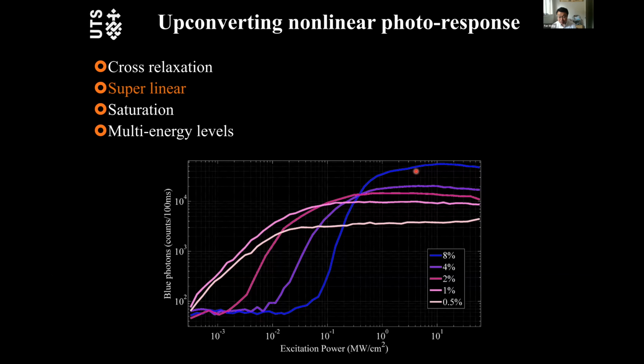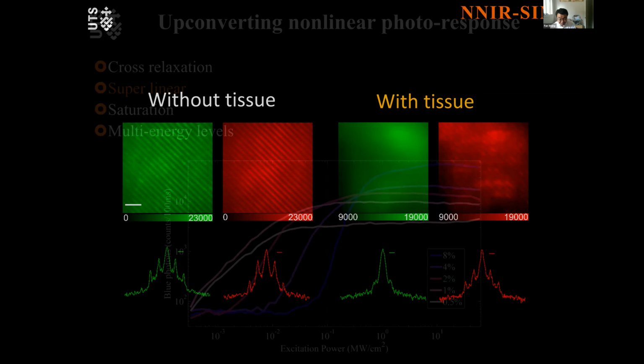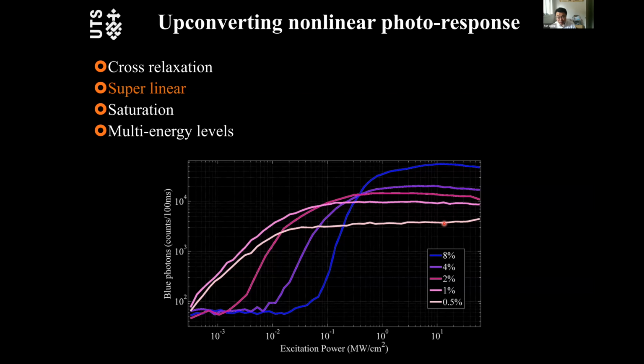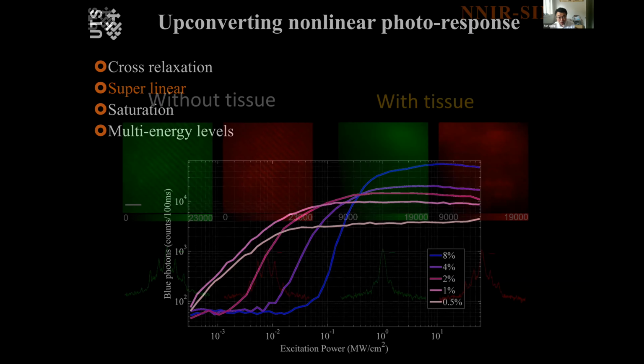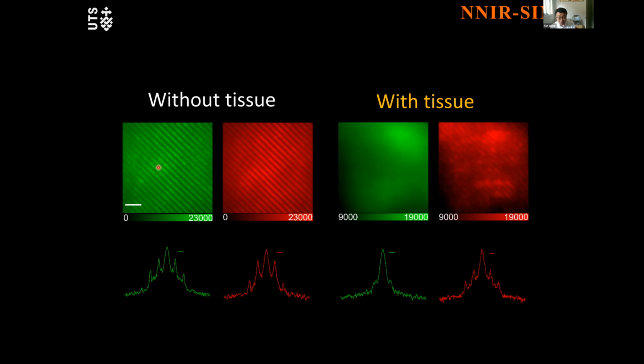And this power-dependent curve means that if you shine some pattern onto a nanomaterial, the response can be different. It would carry more resolution output. Another benefit is, again, the near infrared emission. Over here we have one test. We use green laser, green emission and 800 emission, and without tissue, you can see both of them have nice finger output. But with tissue, because of the absorption, you couldn't see the finger clearly with the green light. But with the 800 emission color, you still can see the finger.